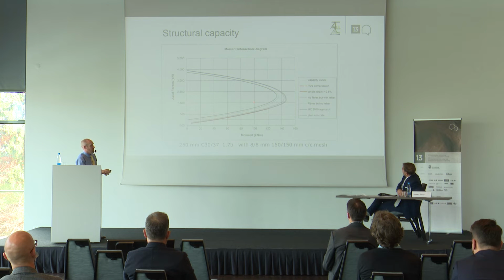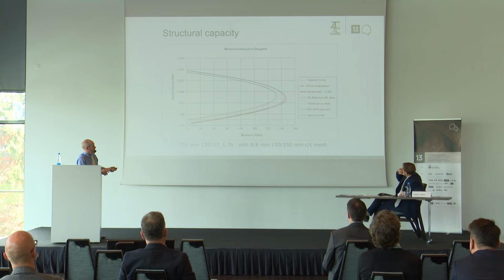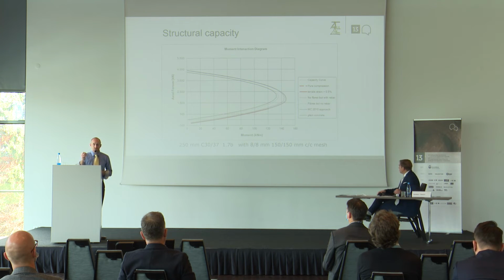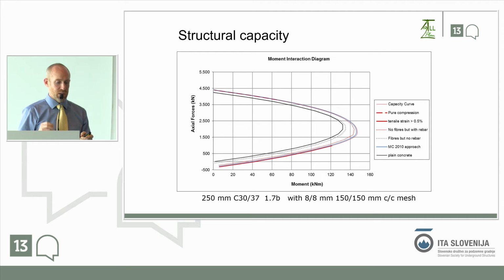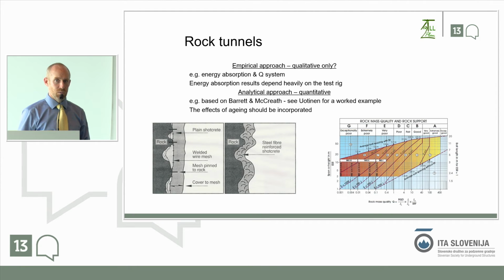So this is if we had nothing, no bars, no fibers or anything, and we add the fibers, you've got this little dotted line. So you can see there's a little bit of gain. You sometimes have a case of hybrid where you have steel bars and fibers, and then in that case again, you can see that the difference between just having bars and then adding fibers with the bars is very small. So it's a small gain in that sense for the bending capacity, but the real win for us is we have the confidence that our material is a ductile one, not a brittle one.